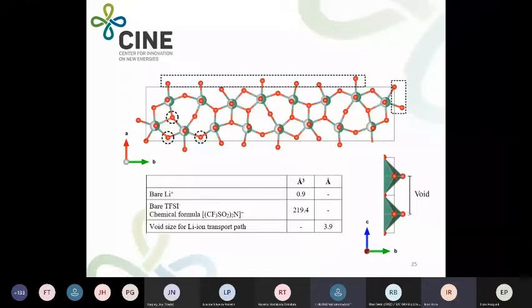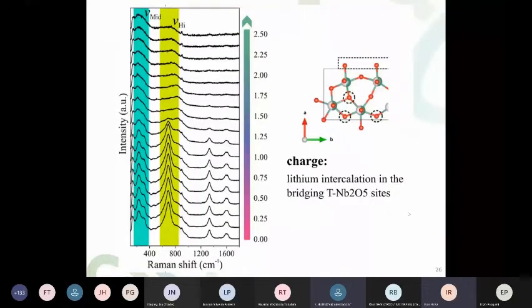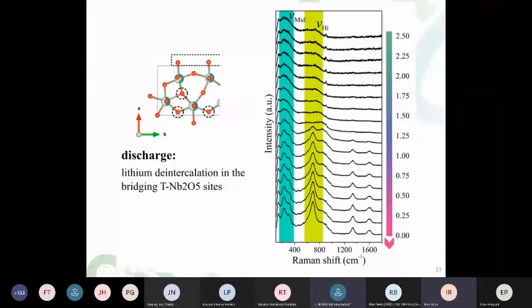Sorry about that. That's what happened here when we charge the cell, the lithium ion gets in, or the sodium ion. The same happened with sodium. The sodium ion gets in the system, and you lose this high frequency and middle frequency related to this voids process on the niobium pentoxide. So we see here on the chart, and we see this one here on the discharge, the reversible process. In this kind of system, we have not only an electrostatic process, but we have pseudo-capacitance, and this takes quite a lot to be charged.